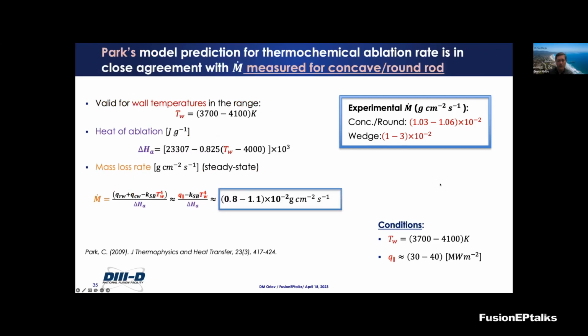Now, the other model that I mentioned was Chul Park's model. If we use the same wall temperature and plug the numbers into his model, we get a mass loss rate of about 0.8 to 1.1 grams per centimeter squared per second. These numbers, if you compare them to the experimentally measured ones, are actually very close to what we had on the concave and round cylinders. We're basically matching the numbers in Chul Park's model with what we've measured.